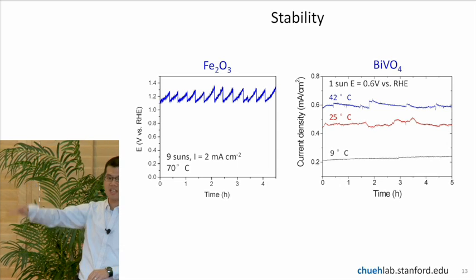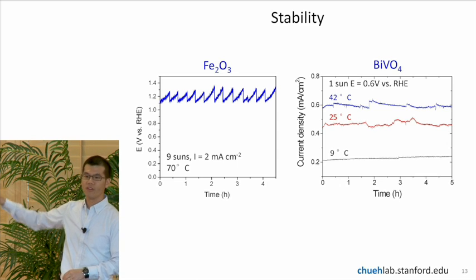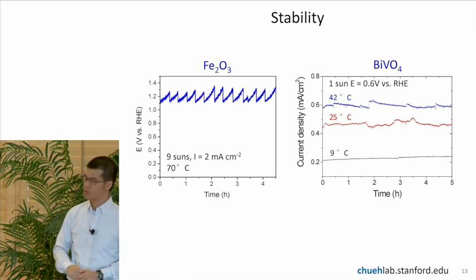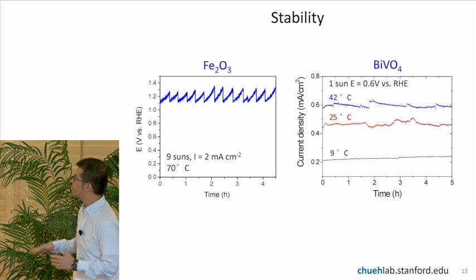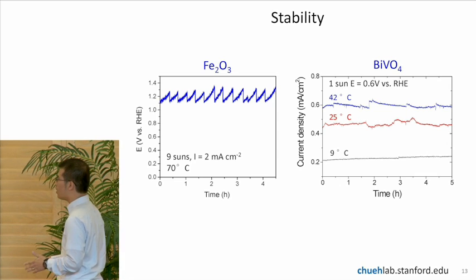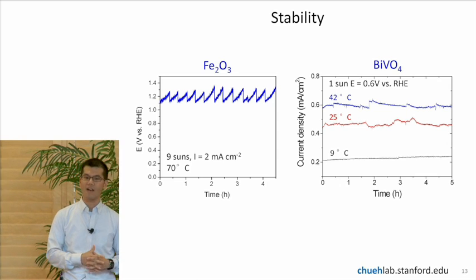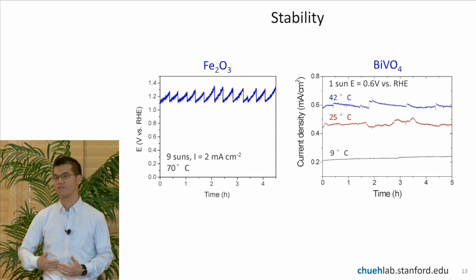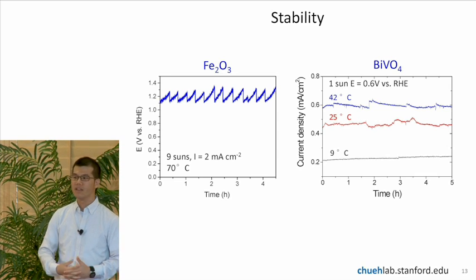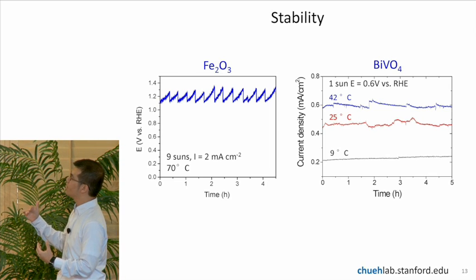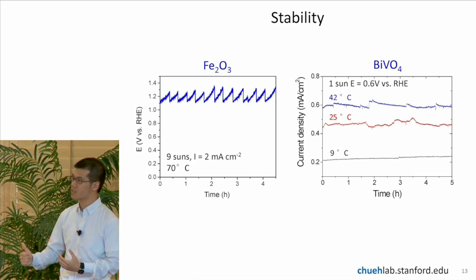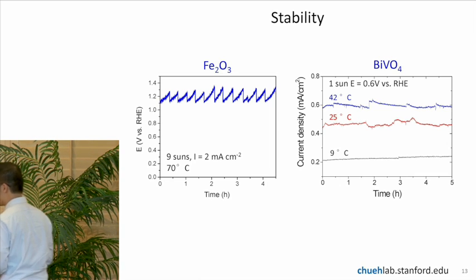The ripples you're seeing are due to the formation of bubbles on the top of the photoelectrode, so don't worry too much about that. But the bottom line is that we have stability over a relatively short period of time, 5 hours. But we have seen stability upwards of 50 hours is also possible as well. And we're working toward improving the stability of the system at even higher temperature.